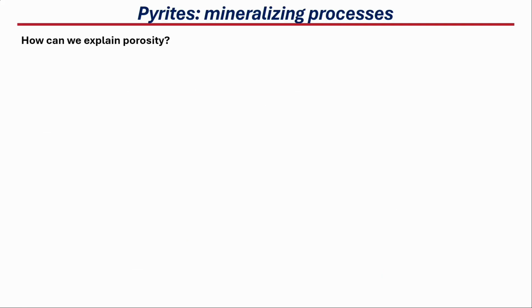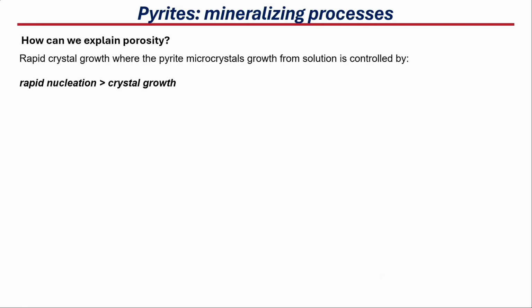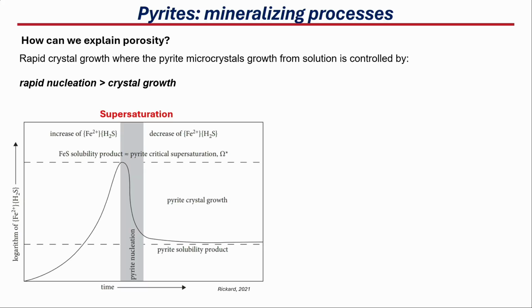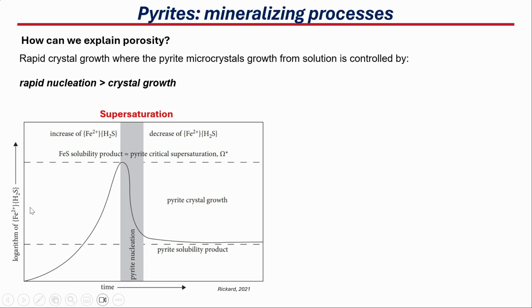So how can we explain then porosity? Well, porosity in different ore deposits has been explained, due to these microcrystals of pyrite, by rapid crystal growth, where we have more nucleation than actual crystal growth. And some authors, such as Rickard, 2021, establish that this process really happens in supersaturated fluids, where in this diagram we have time over here, and the logarithm of the activity of iron and H2S. So we see that we have this supersaturated fluid in these components.